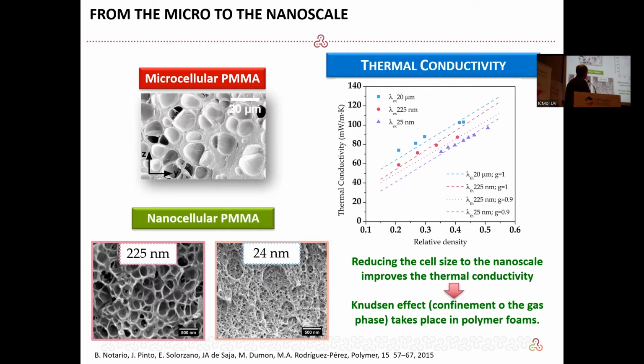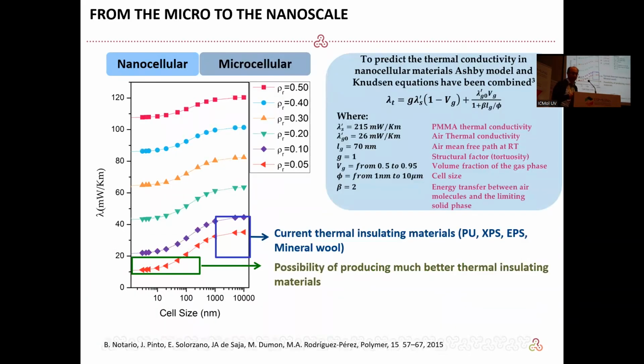And as you see, thermal conductivity versus relative density, we have a decrease as expected, because when we decrease the density, we reduce the amount of polymer, and the gas has a lower thermal conductivity. And as you see, there is a reduction. This is the microcellular polymer, nanocellular with this cell size, and nanocellular with another cell size, smaller. So we are reducing the thermal conductivity. In particular, we can estimate the thermal conductivity by modeling, very simple analytical models to estimate the values as a function of the cell size for a given relative density. So this is what happens. And we have experimental evidences of this.